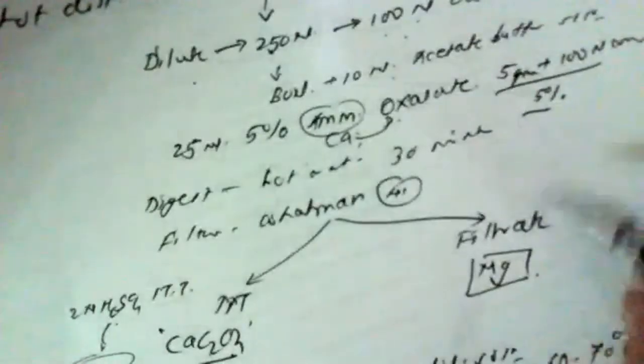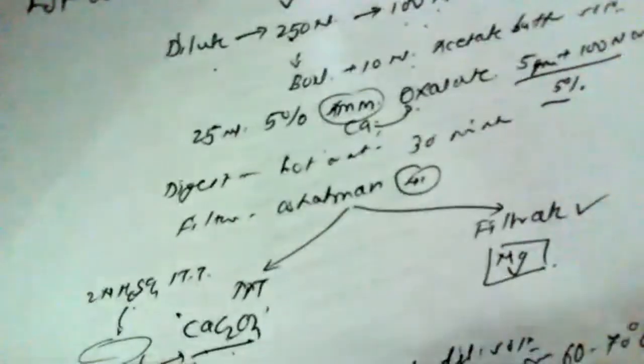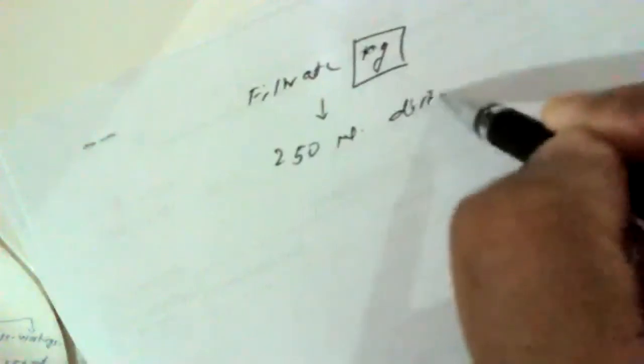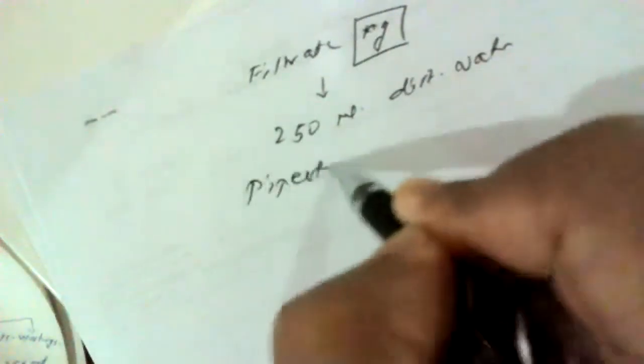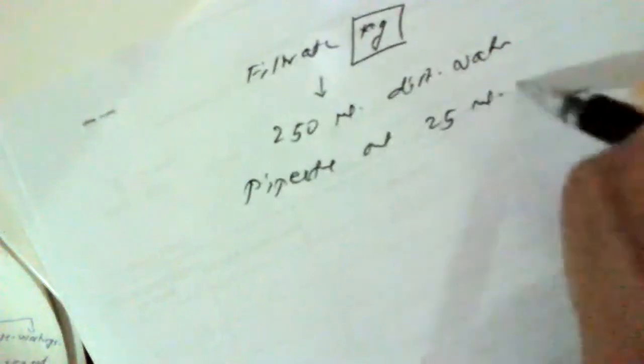Now we are left with this filtrate which contains magnesium. So how can we determine the magnesium content? Just see here. We are with the filtrate which contains magnesium. How to calculate this magnesium? This filtrate is first of all diluted to about 250 ml by using distilled water. Now after dilution, we have to pipette out 25 ml of this diluted solution into a conical flask.